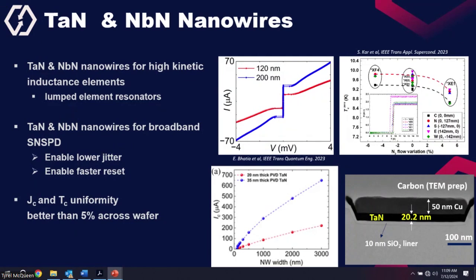We characterized the IV curves for these nanowires, and you can see in this graph how the IV curves look for two different nanowire widths. The IC scales as a function of the width of the nanowire for two different thicknesses of tantalum nitride. And this graph is for the niobium nitride nanowire, and also for the blanket films, where for different nitrogen flow we can vary the transition temperature, as you can see here. So here also we can see the synergy between the fields using the same materials. Like Pops showed one graph where we had the same material, but we could go to different fields. So the same nanowire can be used for single photon detectors, which are used in photonic quantum computing, and it can be used as a kinetic inductor in the lumped element resonator in superconducting quantum computing. So that's how the synergy works.